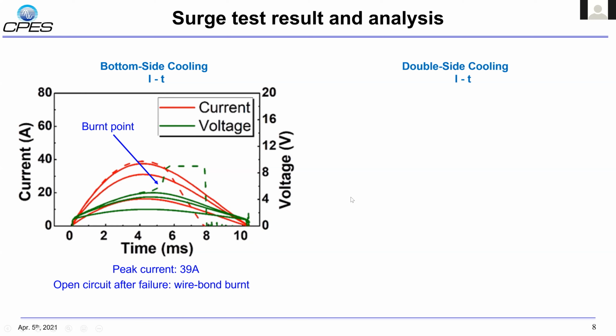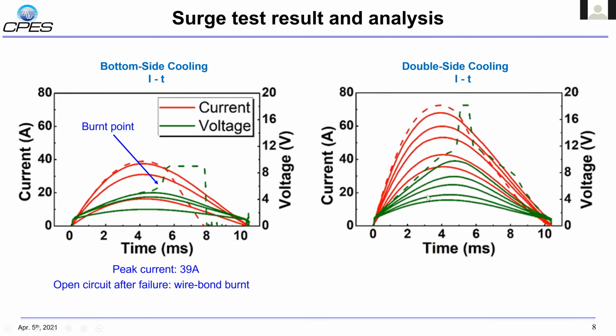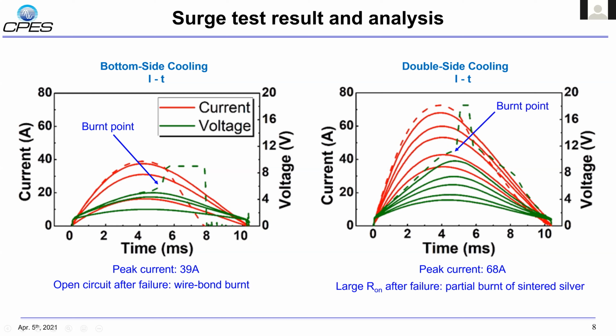And here's the double side cooling. So the peak current that the gallium oxide Schottky barrier diode can endure increases to 68 amp here. Okay, and here's the burning point. So it is not an open circuit after failure. It has a large on resistance after the failure, which indicates a partial burn of the sintered silver contact.